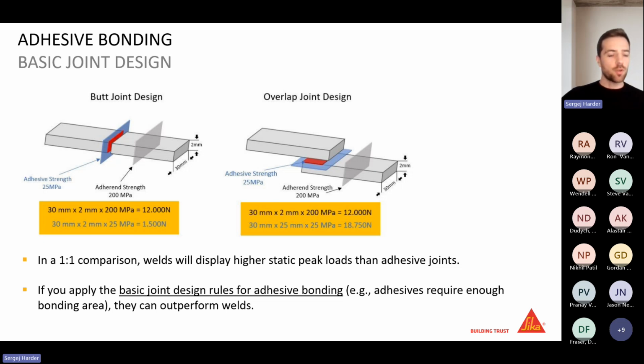And if you just use the cross-section of your metal substrates, the weakest link in that part will obviously be the adhesive, because the polymer in almost all cases has a lower strength than a metal. So for example, we have here some kind of structural adhesive with 25 megapascal. And if you have a substrate with 200 megapascal and you just use the same cross-section to connect both parts, the adhesive will be the limiting part. So here, just as an example, you will be able to transfer 12 kilonewtons through the substrates. And if you only have the adhesive in between using the same cross-section, it will only be 1.5 kilonewtons. So this will be the limiting factor.